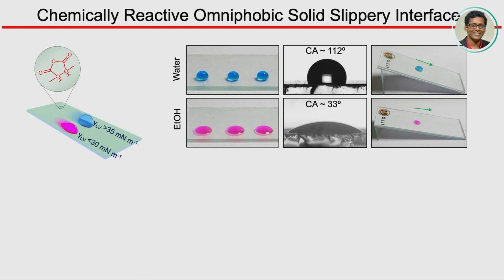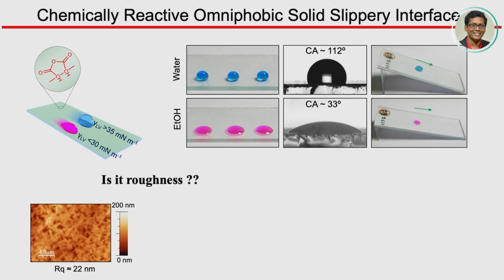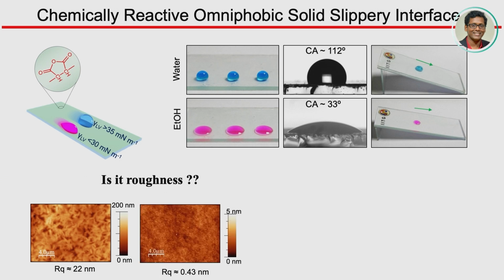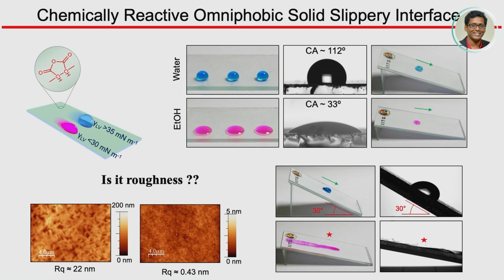Now, what is the reason behind this property? That has not been studied thoroughly in the literature so far. Is it the roughness or the smoothness? So we studied this material and found that the roughness is around 22 nanometers, which is considered a low-roughness interface, and we have the ability to modulate the roughness in this current design. The maleic anhydride and the long-tail hydrocarbon alkyl acrylate composition we can vary, and depending on that we can play with the crystalline domain and the roughness. In one composition you can have a roughness around 0.4 nanometer, so it is a much smoother interface. In that case, the sliding angle against water still remains, but against ethanol it is not working when you make this interface much smoother.